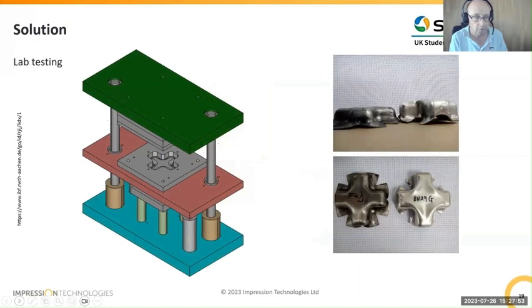The most effective lab test that we've got running on a regular basis at the moment is a small cross die tool that we use. We can make these dies from all the same materials that we make production dies with, and we can also PVD coat them with various coatings, and we can see the effect of those along with different lubricants. We did originally design these so that we could actually cool them, but the rate that we actually run the tests is, generally speaking, much slower than the production run would be. So the dies tend to come back to room temperature between each test anyway.